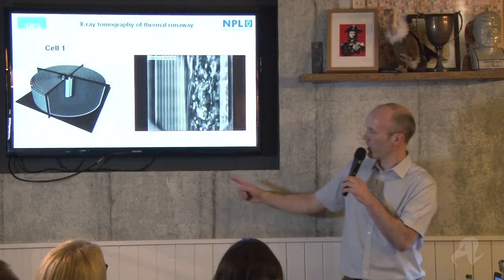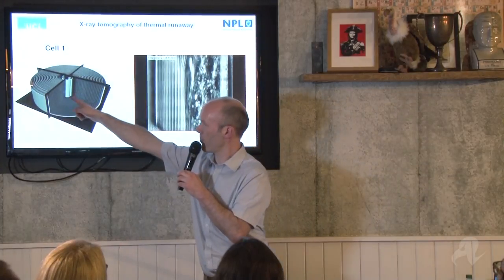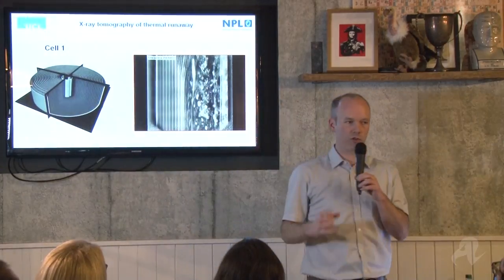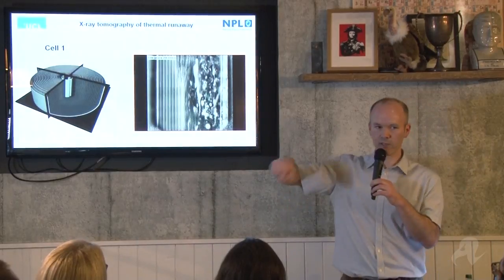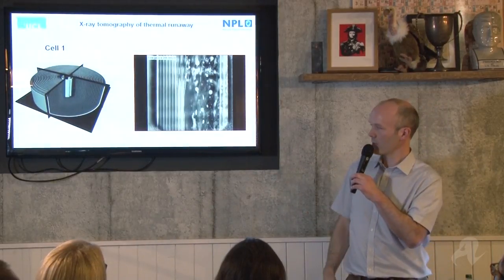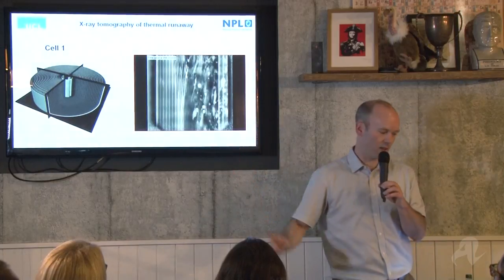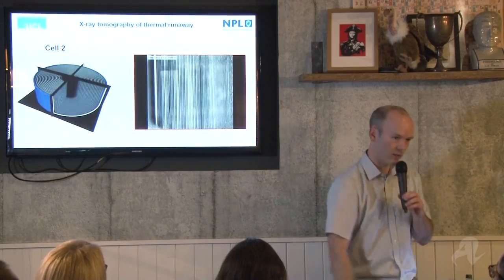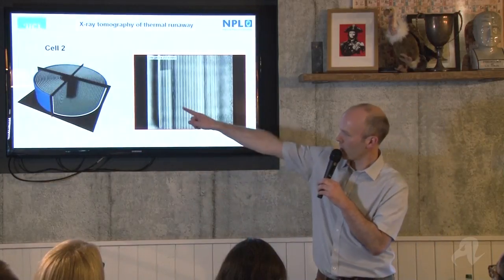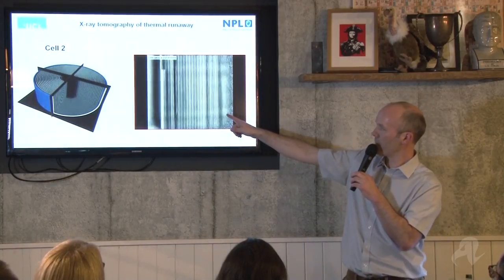So that's one cell. You might notice inside this cell, there's what's called a mandrel. This is a central structural support around which the Swiss roll of the battery is wound. So I'm going to show you what happens when one of these cells doesn't have one. This is another commercial cell, no mandrel. We do the same experiment. You can see from the time scale here that time is moving very slowly. In about 0.1 of a second, we've destroyed the structure of the cell. It's caved in upon itself because it didn't have that structural support in the middle.